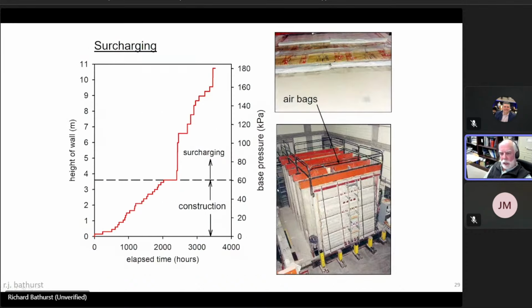In the bottom right is the RMC test facility with our control wall in place. And what we did after the construction, we surcharged these walls, and we did that by inflating airbags that were constrained by these horizontal members that you see in this slide. And interestingly, these airbags are paper with a plastic bladder. They're actually used as void fillers in railway cars that are only partially filled in order to stop the cargo from shifting around. They're really cheap, and they served our purpose to develop uniform surcharging of the reinforced soil surface.